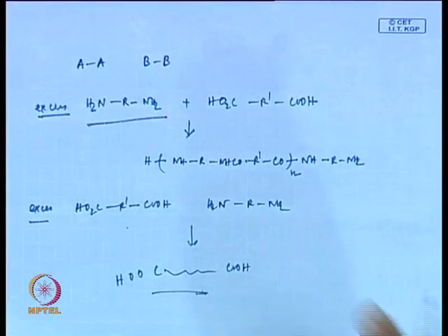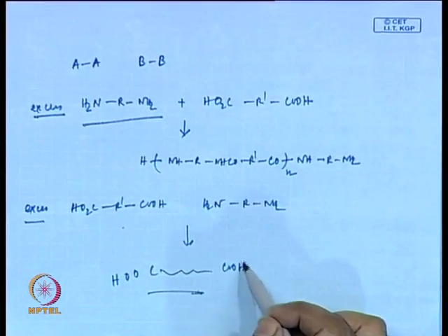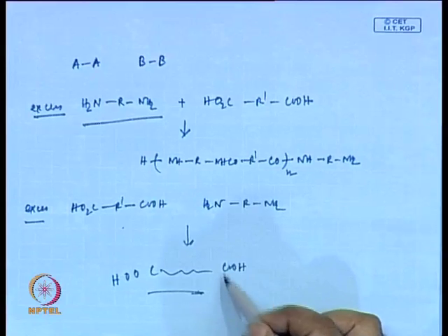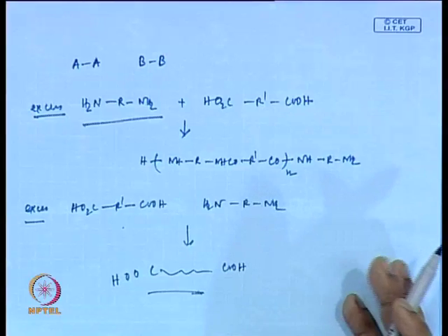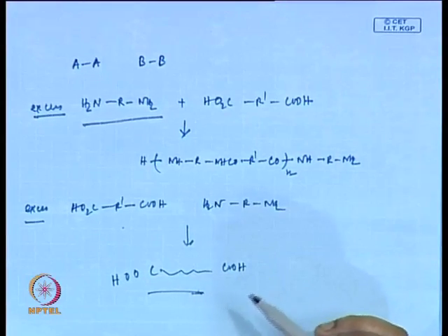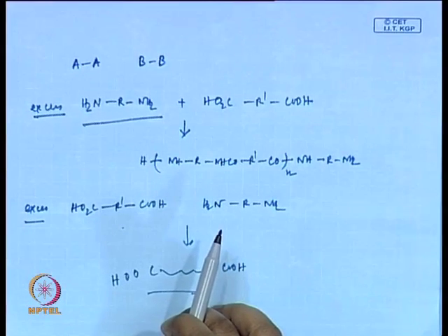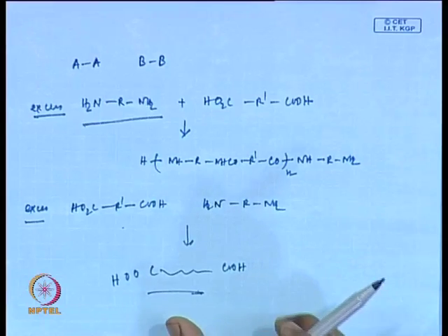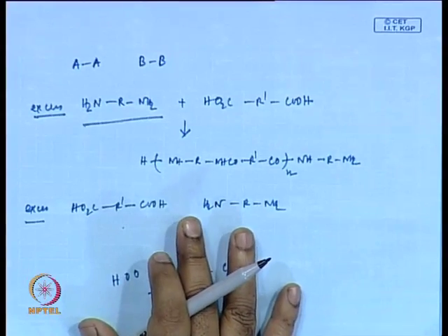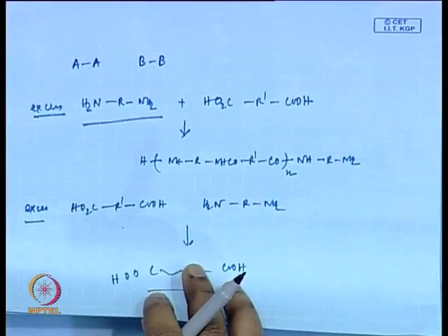When you take these polymers out and do a compounding and molding step, unless you are adding something from outside which will be able to react with either of these leftover functional groups, it will stay as it is. It will not react with the functional groups present in the polymers formed itself. Okay. So, that is one of the strategies of making or controlling the polymer. We will see the quantification, how much excess you have to take to target a certain molecular weight. We will come to that quantification level in the next page.